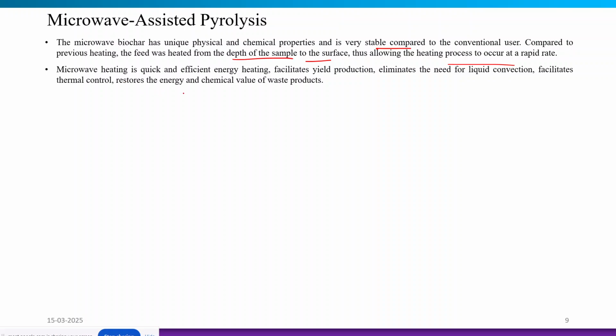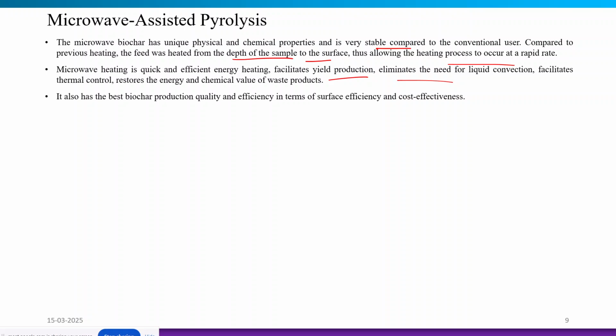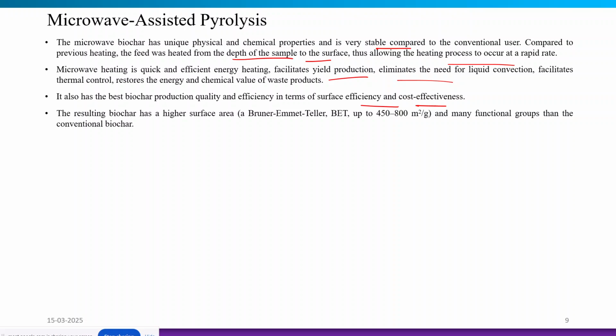Microwave heating is a very quick and energy efficient heating process. It facilitates yield production and eliminates the need for liquid convection. It also facilitates good thermal control and restores the energy and chemical value of the waste products. So it has the best biochar production in terms of quality, and it is also an efficient method in terms of surface efficiency and cost effectiveness. Here the resulting biochar will have a higher surface area, approximately 450 to 800 square meters per gram, and it also contains many functional groups on the surface of the biochar when compared with the conventional biochar produced.